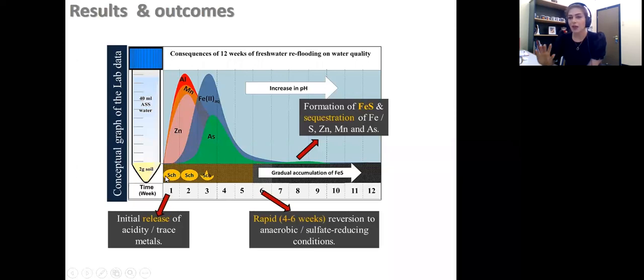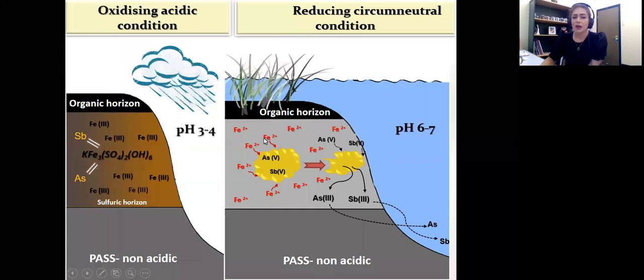But the third experiment that we conducted after finishing these two was based on this part of this diagram, week 2 to 3, when we had the reductive dissolution of schwertmannite and the release of arsenic and the increase of iron 2 in our sediments. The reason that I wanted to conduct the experiment based on these results was that when we have the accumulation of iron 3 containing minerals under